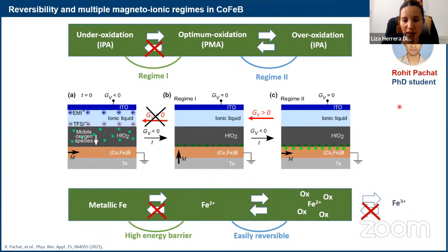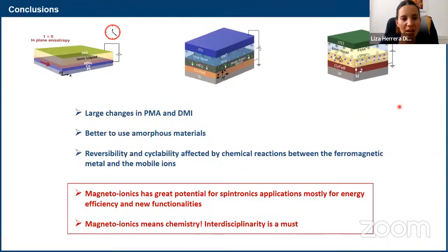So I think I'm towards the end. This is all I had to show you today. I hope I could give you an overview of the topic, and show you a little bit of what we're interested in, which is to learn more about the mechanisms of magnetoionics. In terms of our work, I hope I could show you that we can induce changes in perpendicular anisotropy and in DMI using ionics, that it's better to use amorphous materials because crystalline materials might get in the way of ionic diffusion, and that the reversibility and cyclability are very much affected by the different chemical reactions that can happen between the ferromagnetic layer and the mobile ions.